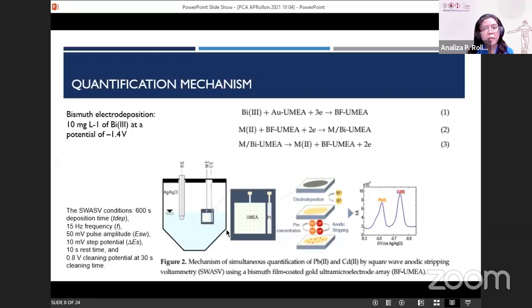And for the working electrode, we have the gold electrode. In step 1, bismuth is electrodeposited on the gold electrode. And in step 2, the metal ions that are deposited in the film of bismuth are stripped using an anodic scan. And that gives us this signal of the current versus the potential applied.